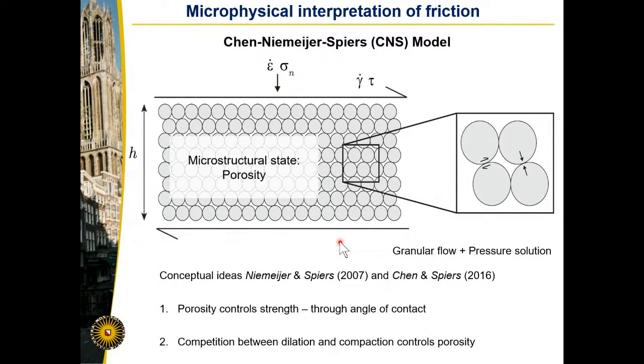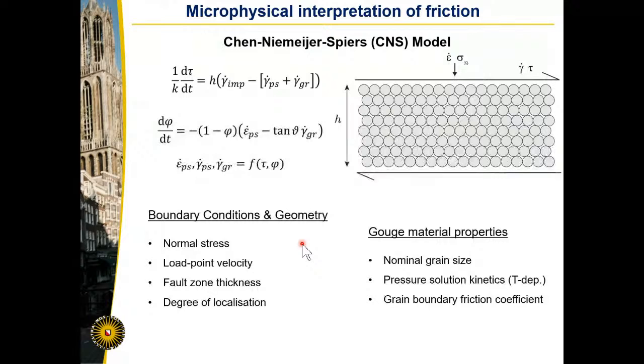The second concept is that as we are shearing this layer, we have two competing processes. We have a slip-dependent dilatation, which tends to increase porosity, and we have a time-dependent compaction, which tends to decrease porosity. Those two will balance out at constant velocity, creating a constant steady-state porosity. But as we go faster, we have less of the time-dependent deformation, so we get a higher porosity and a lower strength.